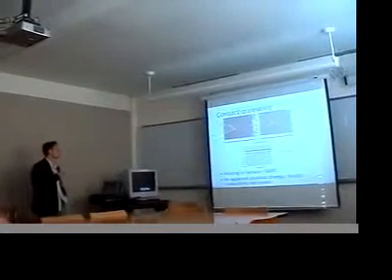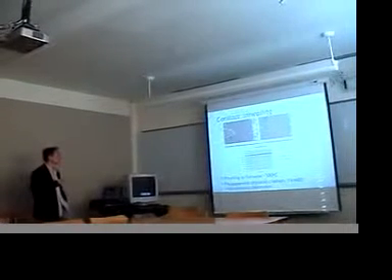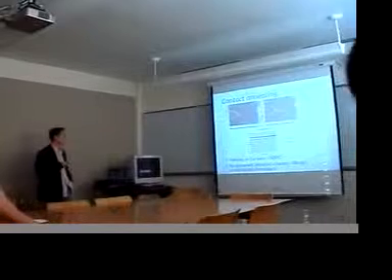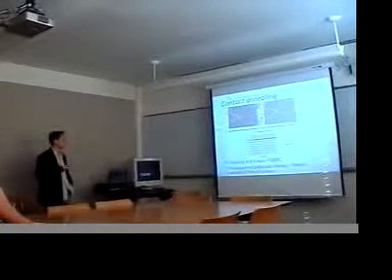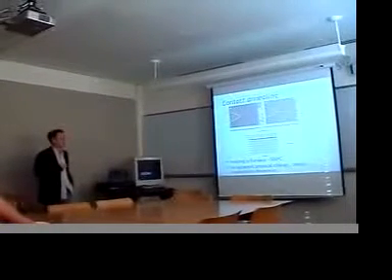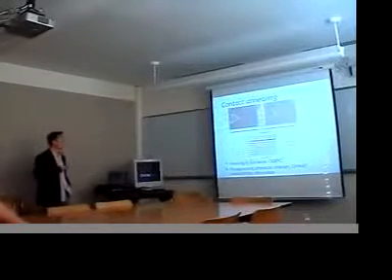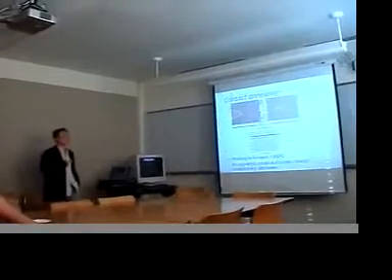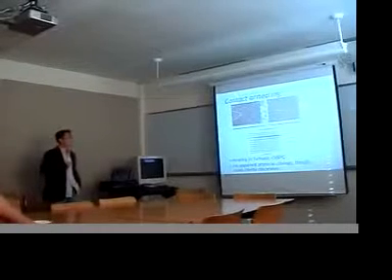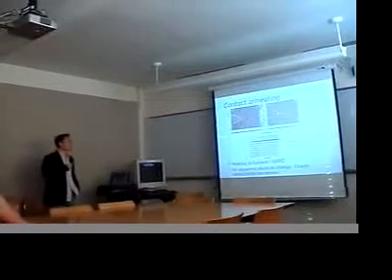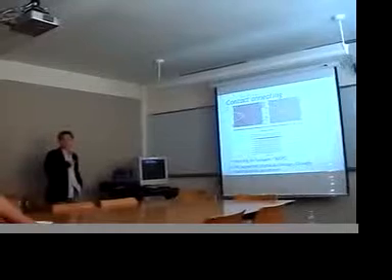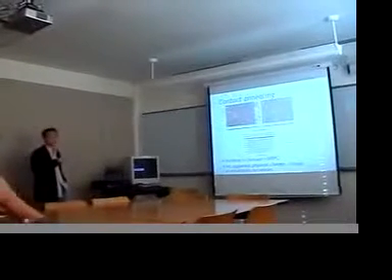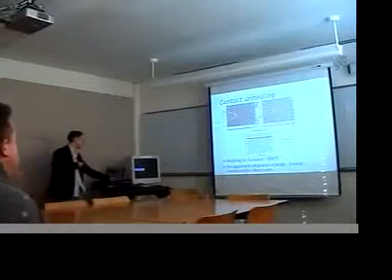As you can see, before and after, things look the same. But instead of an increase in conductivity, it almost became an open circuit. So as of now, I wouldn't say that contact annealing is a no-go. I think it's just that we haven't explored enough of the different parameters to play with in order to improve the contact annealing. But eventually, this should still give us some improvement in the conductivity.